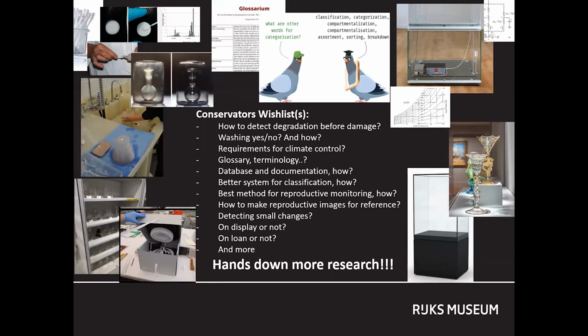The research by Guus, but also follow-up research, such as a follow-up survey done in the Rijksmuseum to create a better condition baseline, documented in word and image and performed by Margot van Schenkel and Roosmarijn van Beemen, but also in another museum performed by Mandy Slager, brought us already many insights, but it also gave us so many new questions. Some of the questions were new, but some were old questions, or questions of which we thought we had more or less the answer to, but still seem to have a lot of uncertainties around them. Like what is the best method to detect early stages of glass degradation? If removable degradation residue is found, should we clean the glass or not? And if so, which method is best for the cleaning of the glass with specific degradation symptoms? And what are the long-term effects of it?